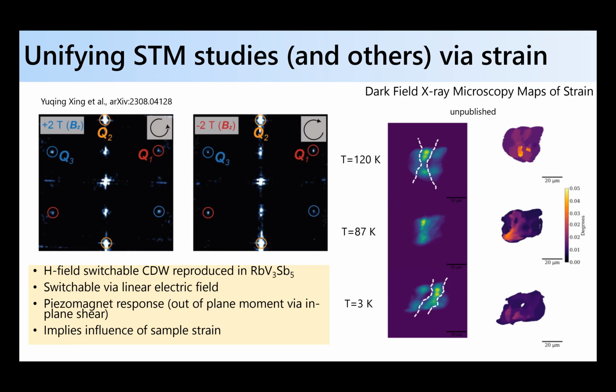So what it means is, if there is any way you break perfect C3 or C6 symmetry, if through some kind of anisotropy, some kind of sample tilting, you always get a difference between 1, 2, 3. Peak intensity will be different. That's nothing to do with chirality. That's nothing to do with chirality. And then with magnetic field, the sample can move. Well, STM in principle is looking at the same. There are all these complications, so I just want to warn about this.